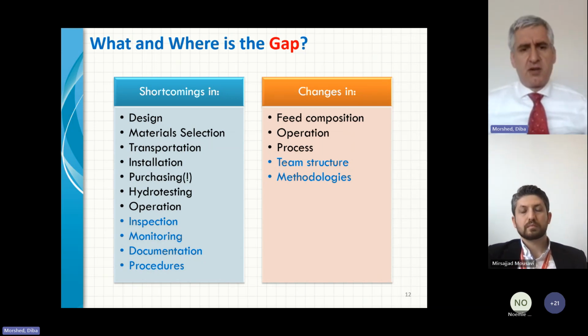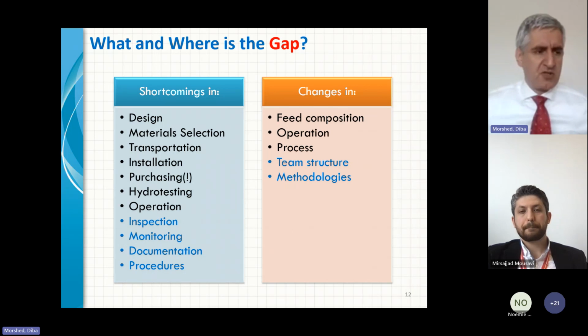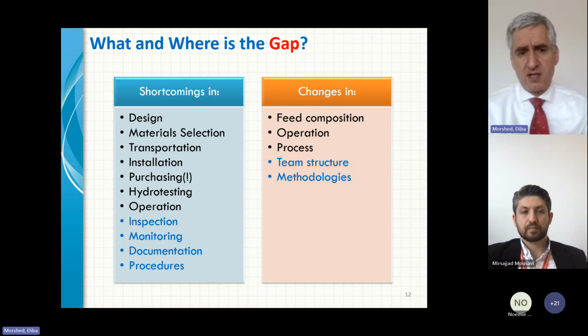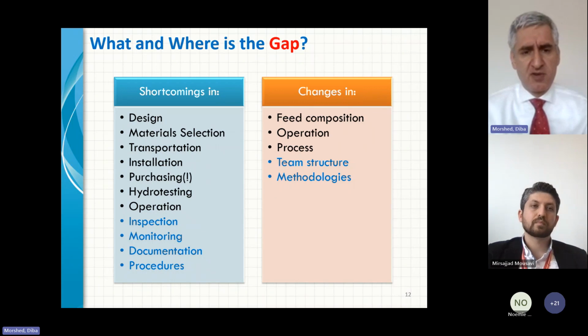Operation is another parameter. Sometimes we make changes to our operation and make some areas of our process systems a dead leg, and dead legs are areas which could suffer from very high corrosion rates, sometimes even several millimeters per year.